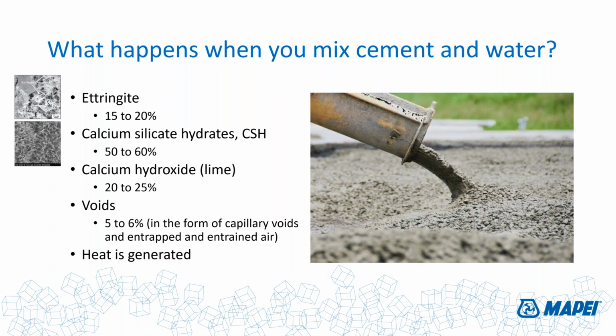All of those silicates and the tricalcium and dicalcium silicates start reacting with the moisture, creating ettringite and calcium silicate hydrates, releasing calcium hydroxide. You're whipping in some air into the thing as well as a bunch of heat being generated as part of the process.